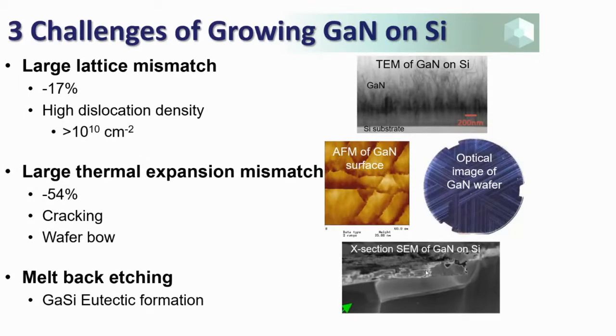So the other problem to solve is that you're growing at 1,000 degrees centigrade, a very high temperature, and the thermal expansion coefficient of silicon and gallium nitride is very different, more than 54%. And when you grow at growth temperature and then cool down, the gallium nitride contracts more. Let's get it right. The silicon contracts, the gallium nitride contracts less than the silicon, and so the silicon puts the gallium nitride into tension, and it cracks. And so you get cracking, very visible cracking. So this is an optical image of a wafer that's really badly cracked. So that's a problem to solve.